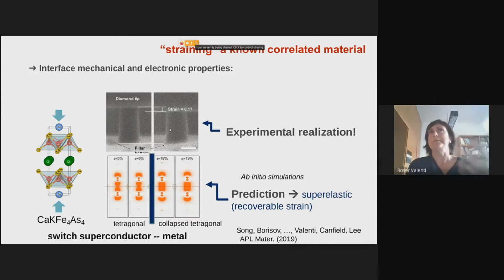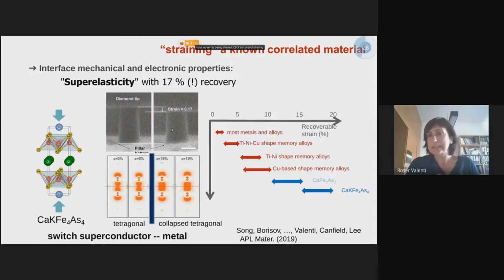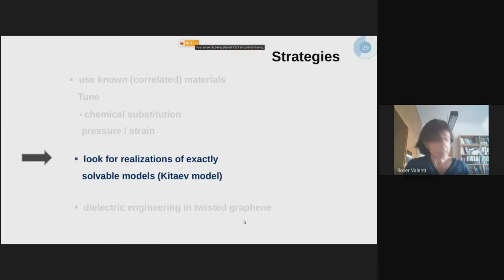So this is what is called a superelastic type of effect. And what is interesting about this material is that the superelasticity is much more effective. The recoverable strain is much larger than in any of the materials known up to the present, like shape memory alloys. So this was a prediction of superelasticity, where you have a mechanical switch between superconductor and metal in a known material.